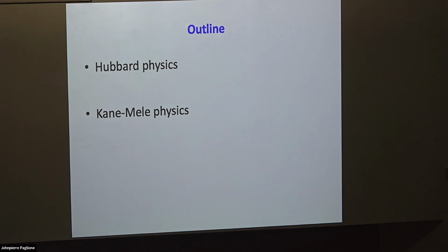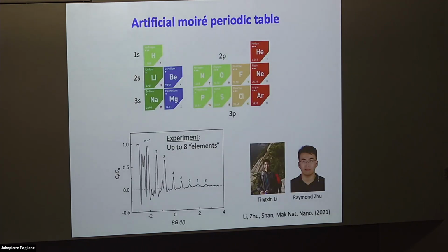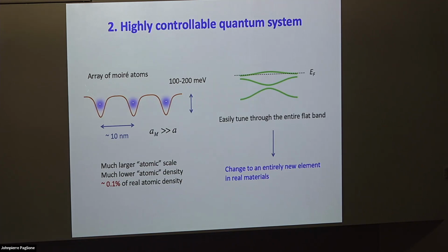Okay, yeah. What do you mean by the artificial atom? Yeah, let me elaborate a little bit more on this. This is actually like an artificial atom. What is an atom? It's just that you have a trapping potential. But this atom, of course, is actually quite different from the real atom. The real atom has a 1/r potential, which goes all the way to infinity at zero distance, right? But when you solve the Schrodinger's equation for a single proton with an electron surrounding it, you have the s orbital, the p orbital, and the d orbital, and so on and so forth. You have something similar here, except that this is more like a harmonic trapping potential, but you can still have the s, p, d type of orbitals in the system.